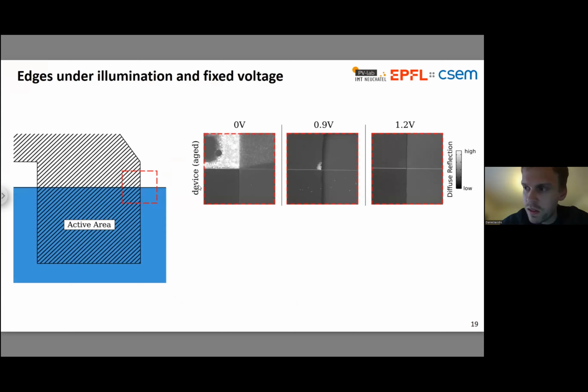Looking at that in a little bit more detail, so I'm showing here images of diffuse reflection. So previous images in black and white have all been photoluminescence, but diffuse reflection is actually quite a useful technique for looking at distributions of degradation, because wherever you have roughening, and degradation is often accompanied by roughening, you have this increase in diffuse reflection. So I'm looking at this little highlighted corner of the device here, where we have four different regions, let's say, of the device meeting in one space. And you can see quite clearly that it's the region of dead space over the ITO boundary that's degrading the most. So that's where we have the brightest region of diffuse reflection, meaning that we have strong roughening in that area.